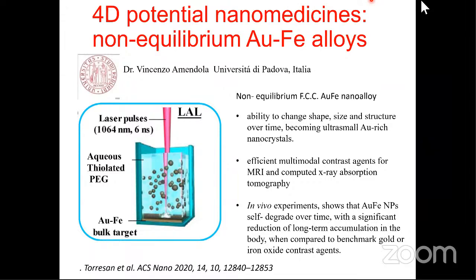So at his lab, he performed laser ablation synthesis. In this case, he used a bimetallic gold-iron target to produce non-equilibrium FCC gold-iron nanoalloy, and we have proved that this nanoalloy has the ability to change shape, size, and structure over time, becoming ultra small and Au-rich, and it's efficient as a multimodal contrast agent for MRI and computed tomography. I will also show some in vivo experiments showing that gold-iron nanoparticles self-degrade over time, with significant reduction of long-term accumulation in the body, particularly in the spleen.